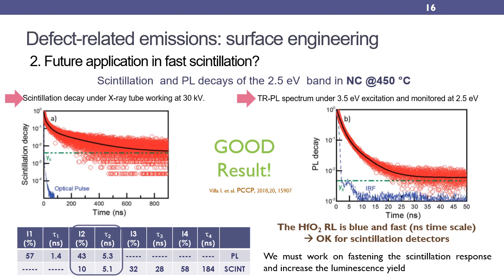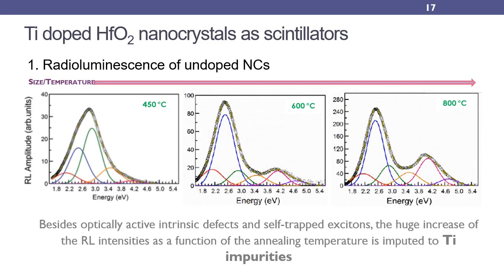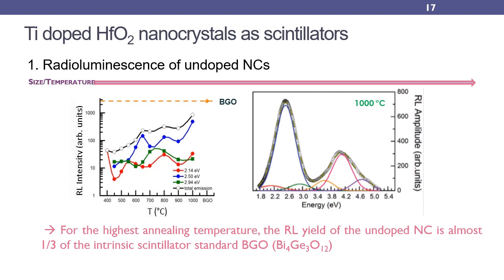Further optimization of the hafnia timing response and light yield can be pursued through the optimization of the synthesis and the post-synthesis treatment. In parallel to the exploration of the intrinsic luminescence of hafnium oxide and the investigation of strategies to optimize the emission output, we should consider the way to exploit the titanium-related blue luminescence in hafnia. Indeed, even when titanium is present in the hafnia lattice as impurity, the blue emission related to it displays a huge increase as a function of the temperature and the nanoparticle size. For samples annealed at 1000 Celsius degrees, the intensity of the radioluminescence emission due to titanium is close to the one of the BGO standard.